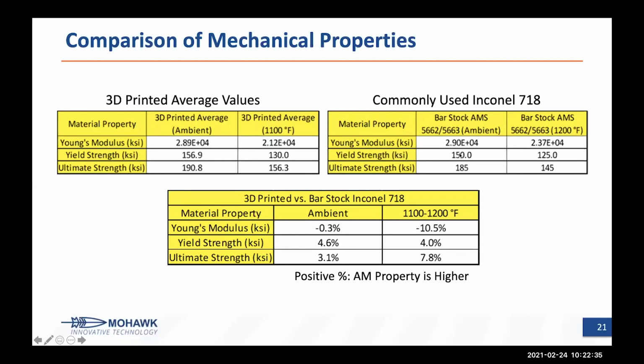We're a little higher in yield strength and higher in ultimate strength when you compare the printed versus the common bar stock. Similarly, we're higher in yield strength and in ultimate strength, but lower again in the Young's modulus, and that's summarized here. And if you look at the variations, it's really not significant, given that we have a very, very small sample size.